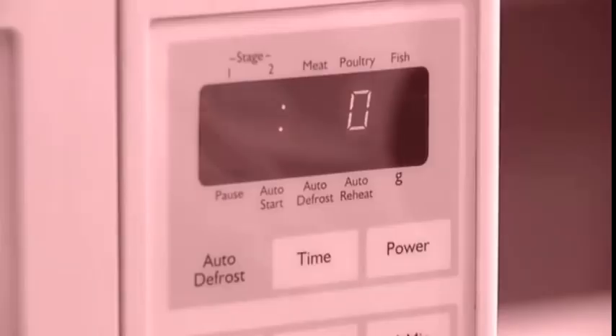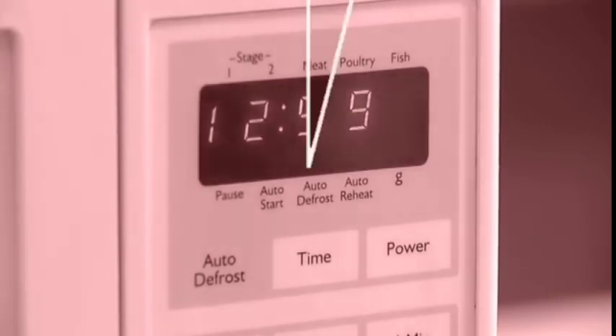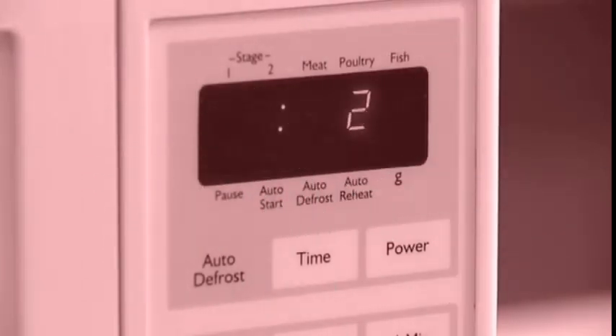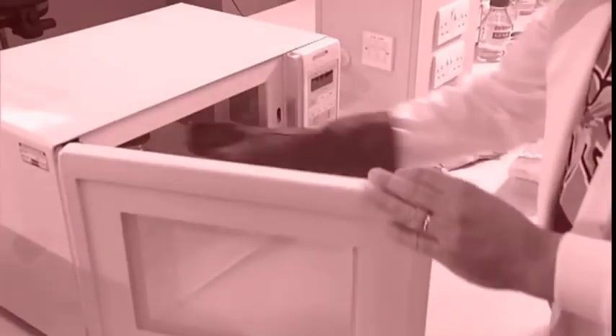When making an agarose gel, don't leave the gel solution unattended while it's heating in the microwave oven. A solution that's heated for too long will lose water, increasing the agarose concentration of the final gel, or even burning the gel mixture.